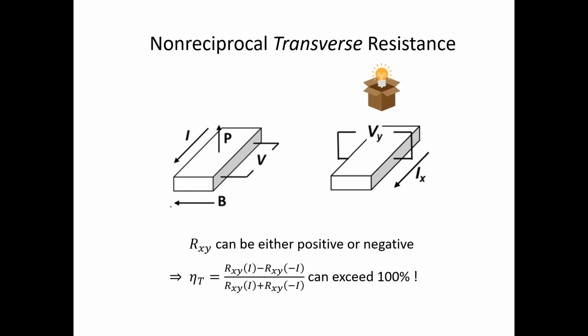However, if we think outside the box, we can actually achieve an even greater diode effect by going into the transverse direction. If we think about a transverse resistance, meaning that if I pass current in the X direction, I measure the voltage in the Y direction, the ratio of the two defines the transverse resistance. So unlike the longitudinal resistance, which has to be non-negative, the transverse resistance can be either positive or negative. And this means that if you again look at the diode coefficient, this can actually even exceed 100%.